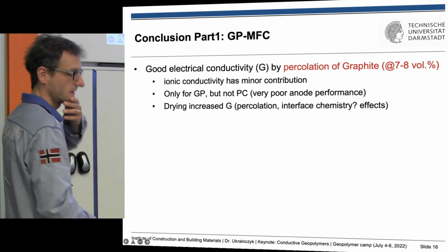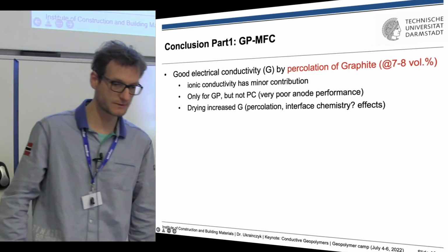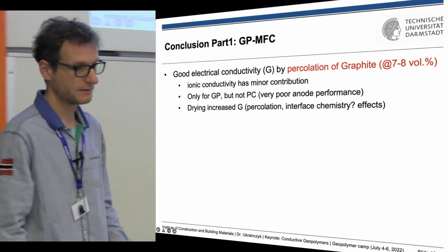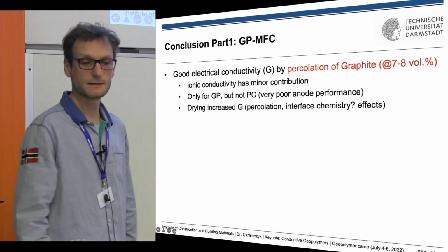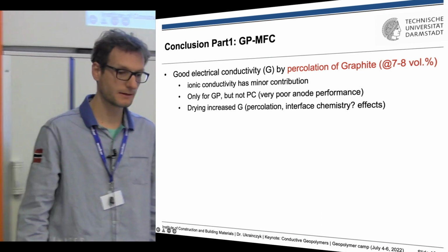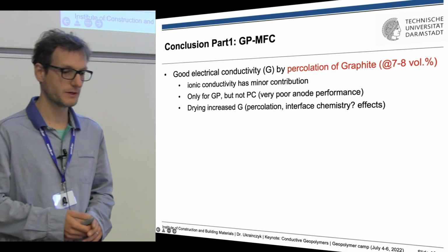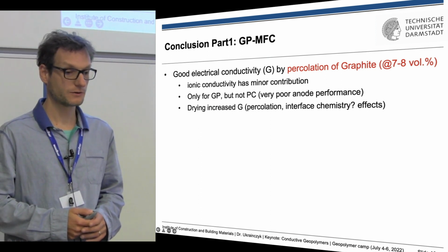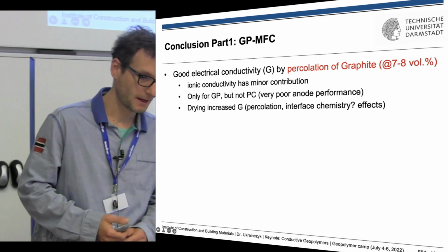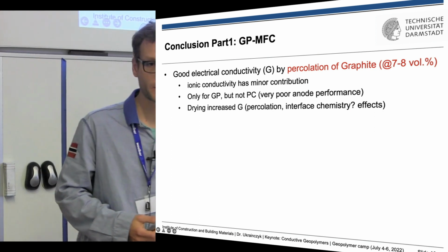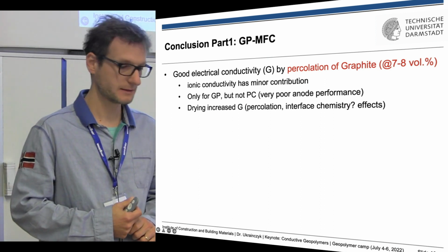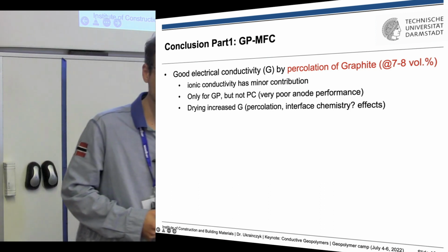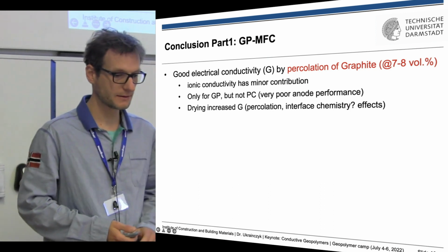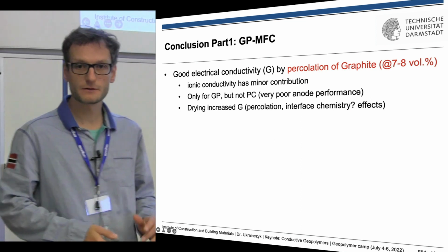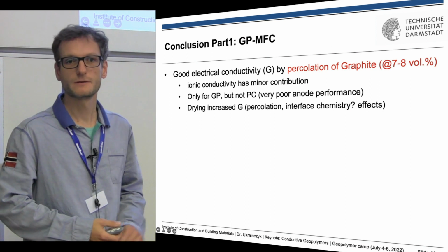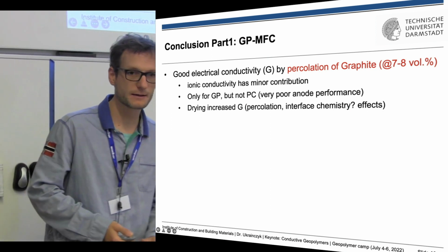So now to conclude this part on the geopolymer microbial fuel cells, actually it's the anode, how to make the conductive anode from the geopolymer, and we can see that we have a very good electrical conductivity, but for that we need the percolation of graphite, which we achieved for geopolymers, and was not possible to achieve for Portland cement systems. And 7 to 8% was the percolation threshold when this graphite starts to percolate. So this is a good percentage for good conductivity. And I would say that the ion conductivity has only minor contribution. So mostly it's from the conductivity through the graphite, which we also proved by drying the material.